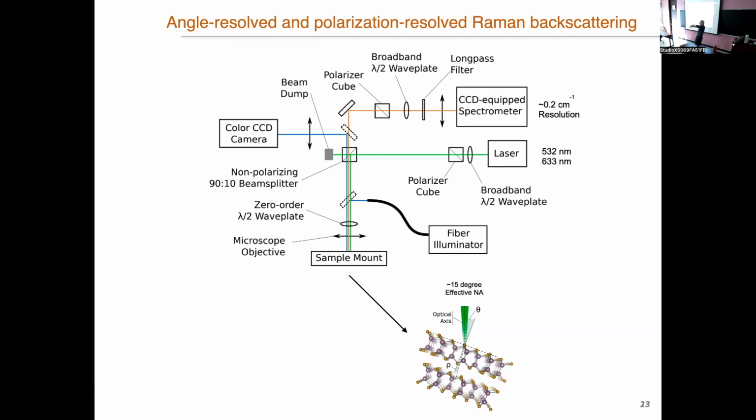And the in-plane wave vector is equal to 0. Now, if you tilt the sample, you have the light that goes like this, comes back like this. That corresponds to a polariton that propagates in a slight in-plane direction. So by tuning this angle with the light, that will allow us to launch polaritons with different wave vectors.